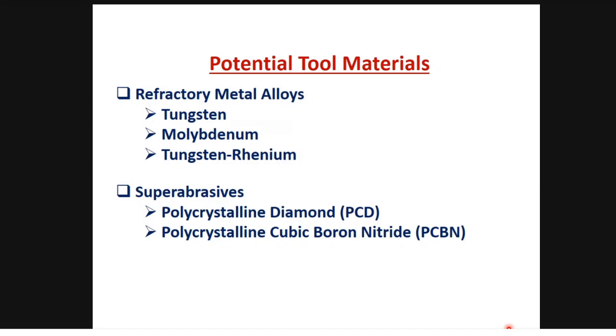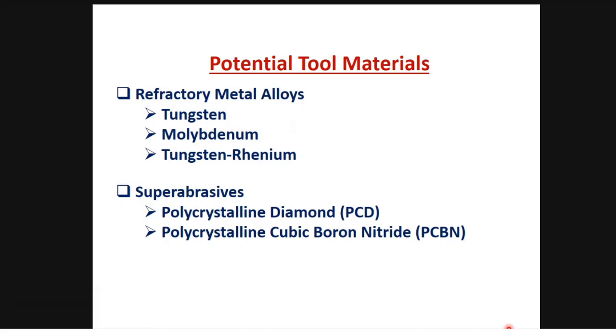Only the pin and the shoulder portion is made separately, because you can make the full tool from these, but the cost is very high. To reduce the cost, they make only the shoulder portion and the pin portion from PCBN or PCD, and that is mechanically clamped with a tungsten rod or tungsten-based alloy rod. But the refractory metals, tungsten, molybdenum, and tungsten rhenium, are now widely used for high melting temperature materials.